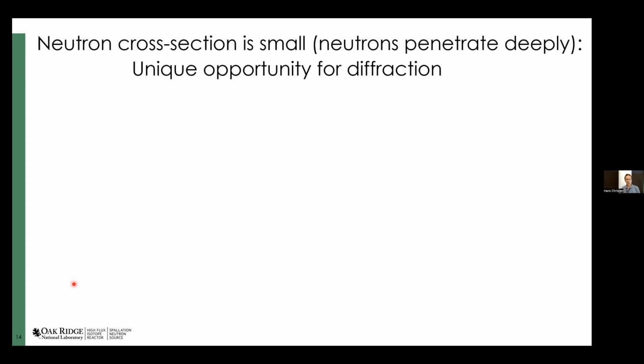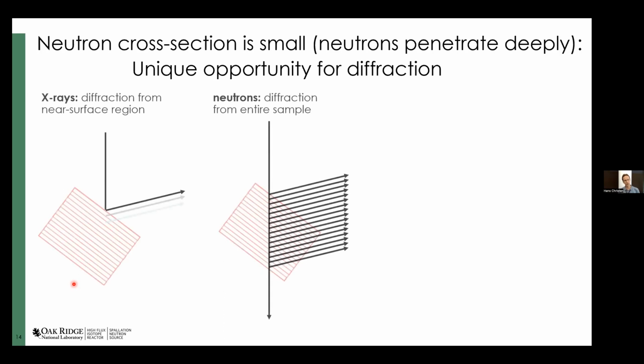Because neutrons penetrate deeply through a material, we can use this for other things, and particularly in diffraction, this is exciting. If you compare X-ray diffraction to neutron diffraction, X-ray diffraction is great because you can focus an X-ray beam to an extremely small volume, a very small spot, and you can do a very precise analysis of a very small part of your sample, as long as it's near the surface of the sample. Neutrons, on the other hand, will give you the average information of the entire sample because the neutrons will go through the whole sample. That is very useful because it gives you much more accurate information about many things.